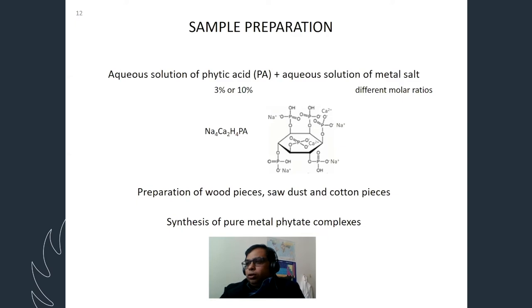The sawdust we dipped in water and stirred with a magnetic stirrer for 10 minutes, and then filtered and dried in air for 24 hours. And wood pieces we also dipped in the different solutions.